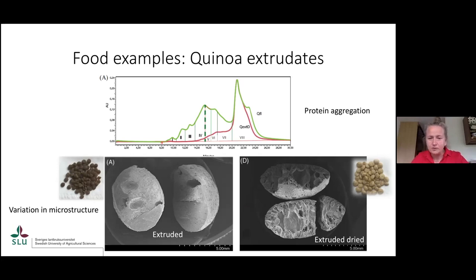We compared the microstructure of the extrudates. The one on your left is the extrudate as it comes. The one on your right is extrudate that has been post-processed with temperature, which means that it has been dried at a high temperature for a very short time. From outside, you see color differences, but they look very similar. From inside, as you could see from this microstructure, they look entirely different. The one on the left is very compact, the one on the right is very porous.